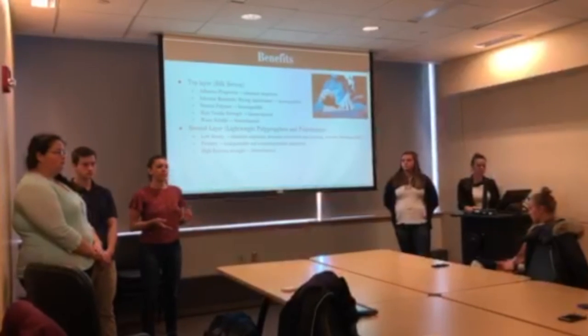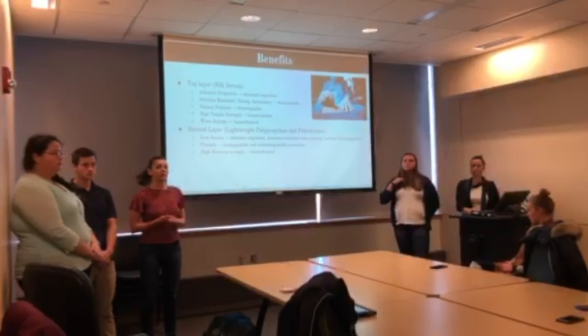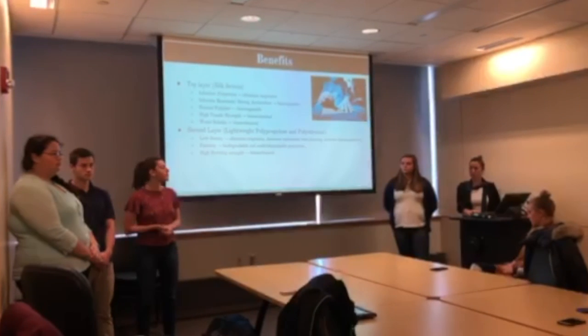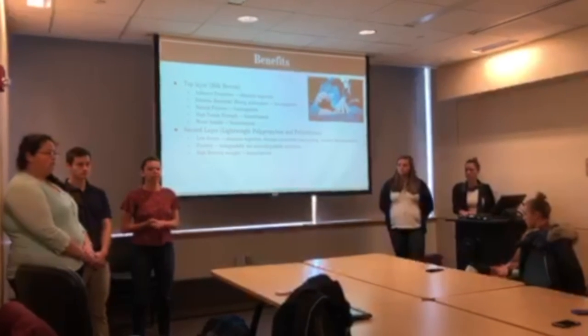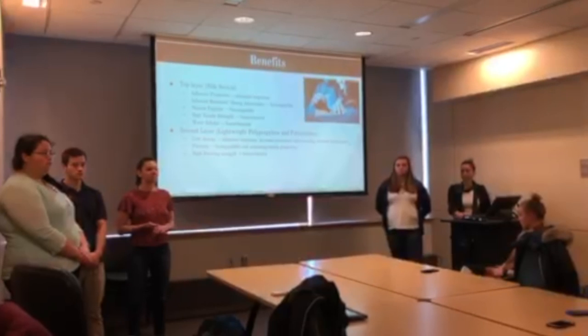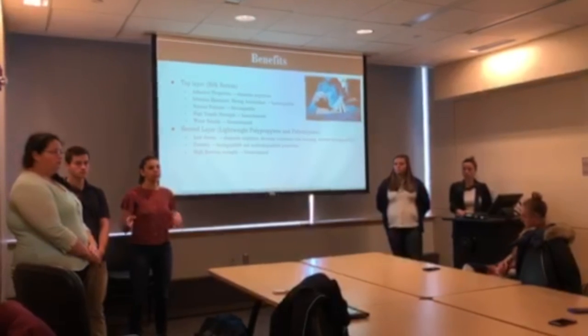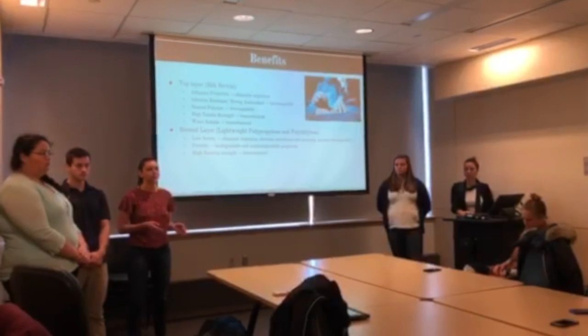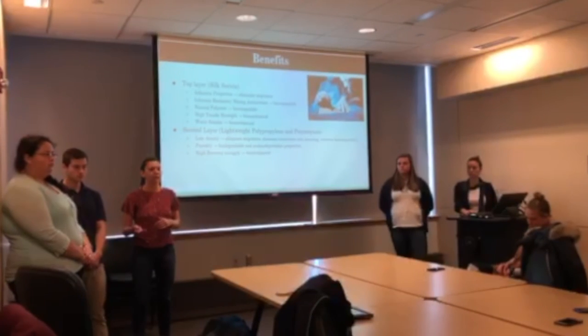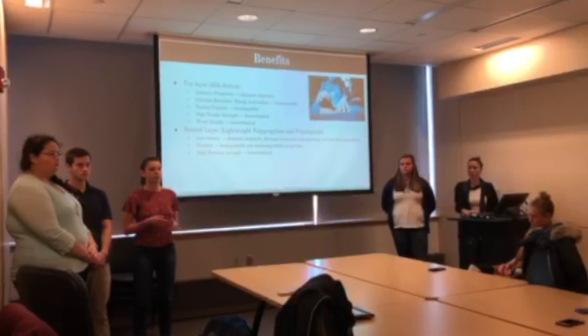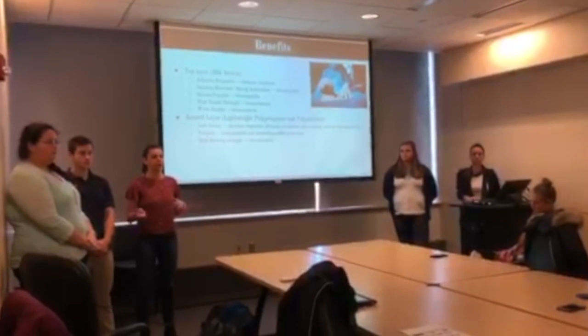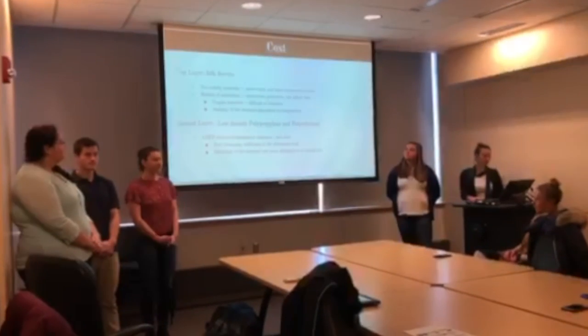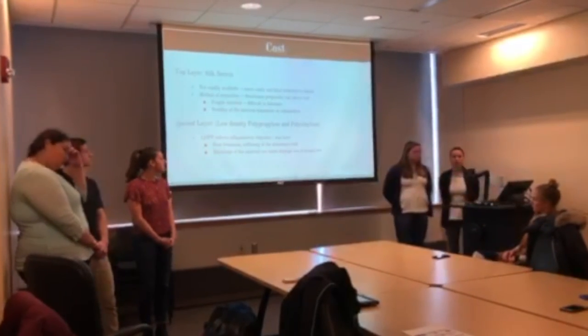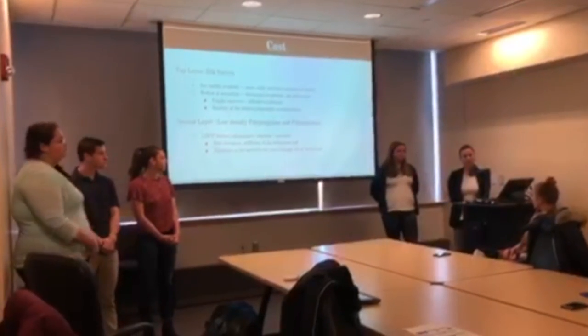And then also the material is very close to the natural tissue properties, so the high bursting strength of high weight polypropylene, which is used today, is 6 times the bursting rate of natural tissue. And we're proposing to have a low weight polypropylene, which is only 2 times, which is definitely a lot less weight and more appropriate. Silk sericin is a natural polymer, which makes it more difficult to sterilize and mass produce.